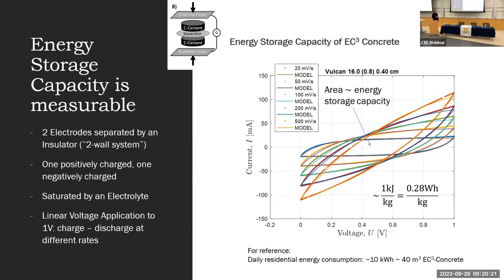Now, as engineers, I want you to forget that this is current and voltage. Just think of this as a stress and this as a strain. Then you have exactly the same mathematical framework as we engineers classically deal with for creep behavior of materials. But what we're able to show here is that we basically get something like 1 kilojoule per kilogram of material inside the system.